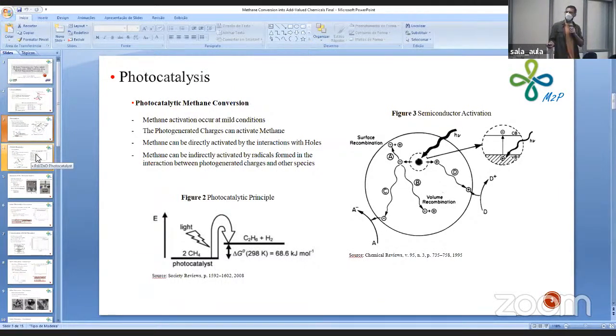We first start here with the irradiation of the semiconductor. Its energy has to be equal to or higher than the energy associated with the gap between the valence and conduction band of the semiconductor. When absorbing the light photon, an electron can jump from the valence to the conduction band, thus producing a free electron and a free hole of positive charge character that can react.